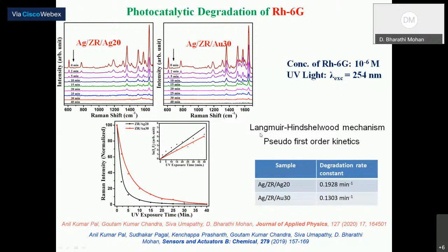So the photocatalytic degradation is described by a Langmuir-Hinshelwood mechanism, which follows a pseudo first order kinetics. The degradation rate constant is calculated from these two straight line plots, and it is found to be 0.1928 per minute for silver, and for gold it is about 0.1303. So the degradation rate constant is much better in case of silver as compared to the gold-based hybrid structure.